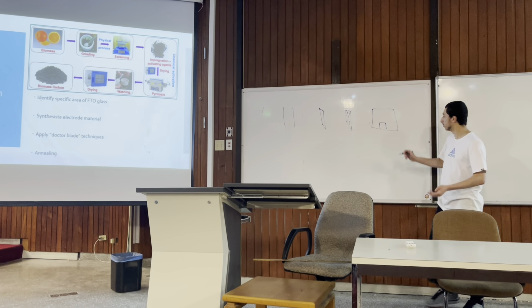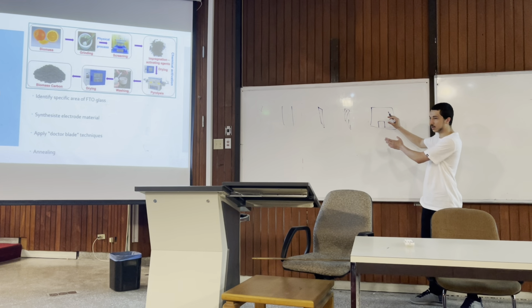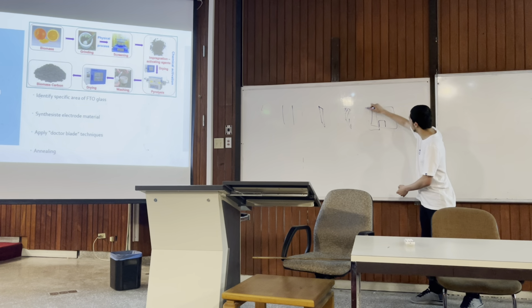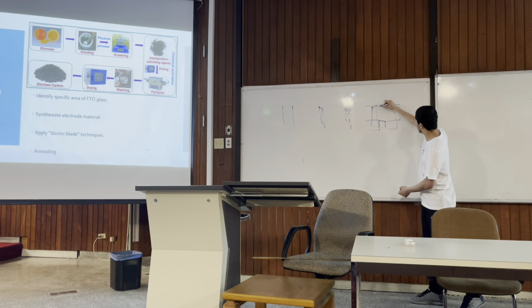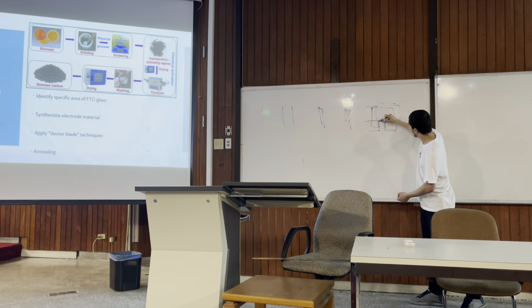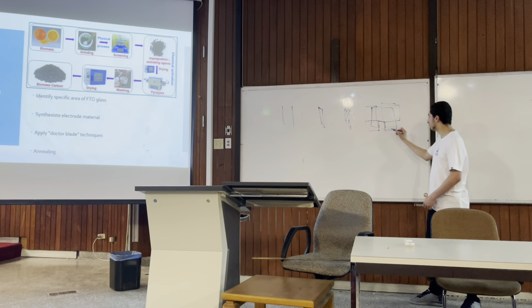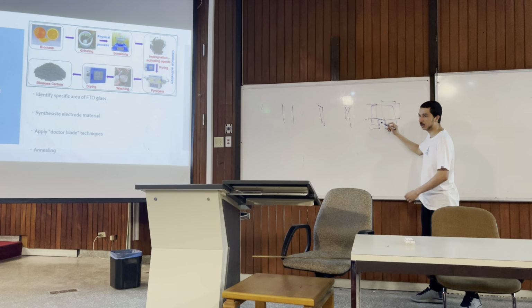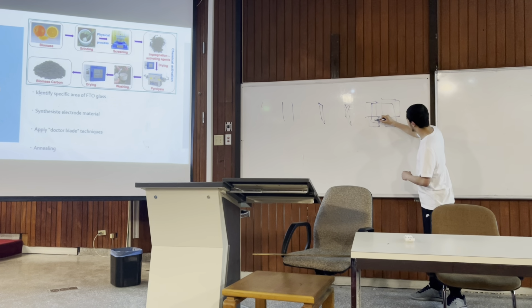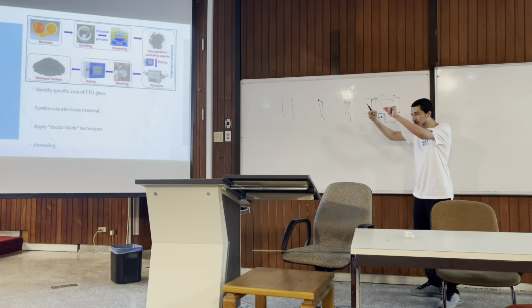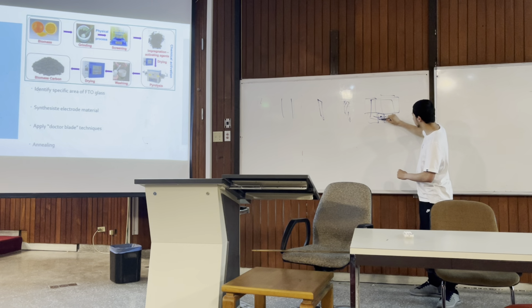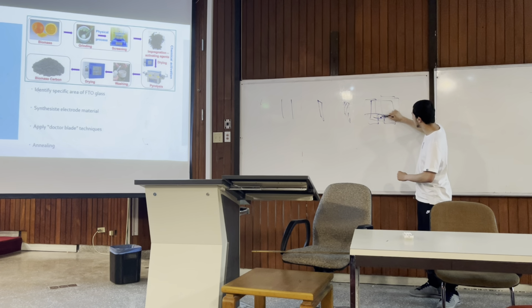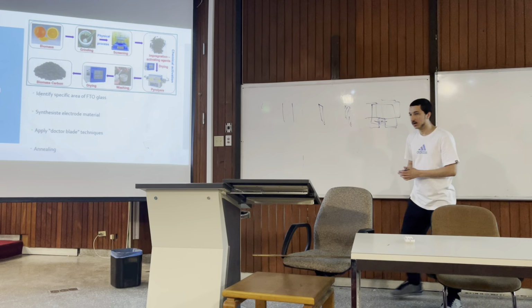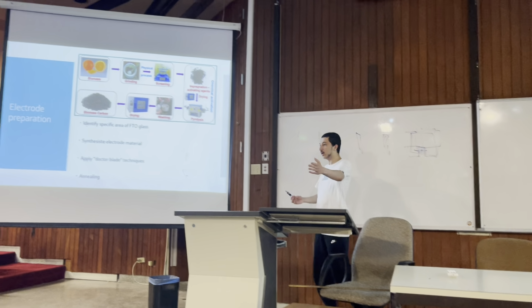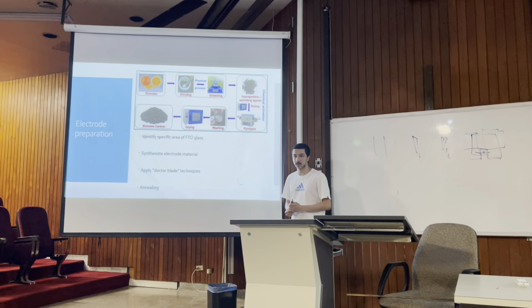Practically, we write with a pencil to identify the area. We put sellotape here, here, and here. Then we apply what's called the doctor blade technique: you put lots of carbon here, take almost like a rod, press down and smudge it all over, then do it again and again until it covers the whole area uniformly. Then we do annealing.